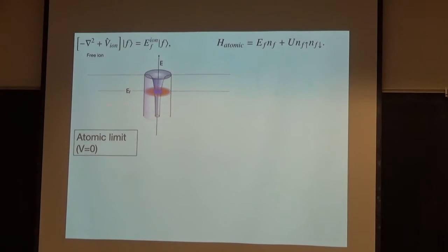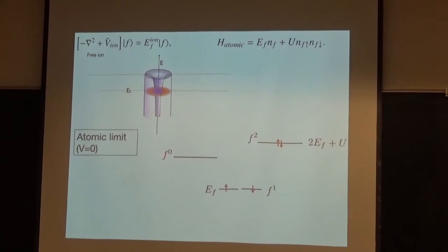So the atomic limit of this model is when you just turn off the conduction sea. This is just then an ionic state. This is then the simplified atomic or ionic model, and it contains three states: one empty state, one magnetic state, which has a twofold degeneracy, and one doubly occupied state. And of course, there's a condition for when this system is magnetic. For this system to be magnetic, the f1 state has to be lower than the f0 state, so E_f has to be negative. By contrast, the f2 state has to be larger than the f1 state, so U plus E_f has to be greater than zero.